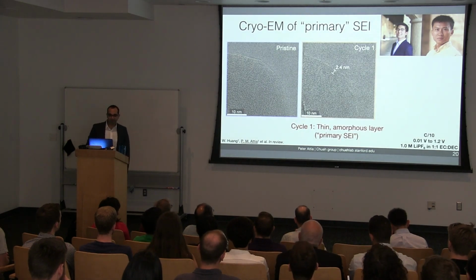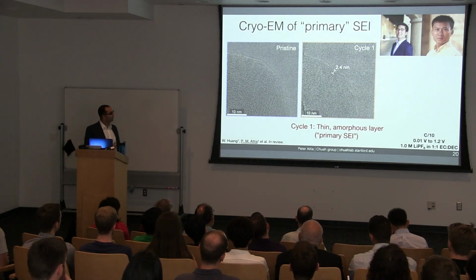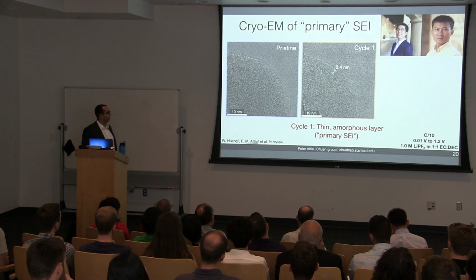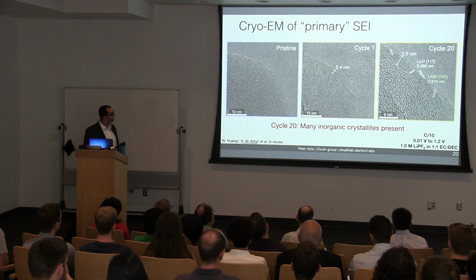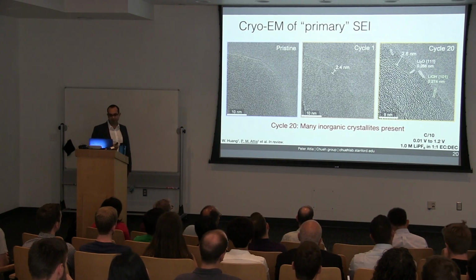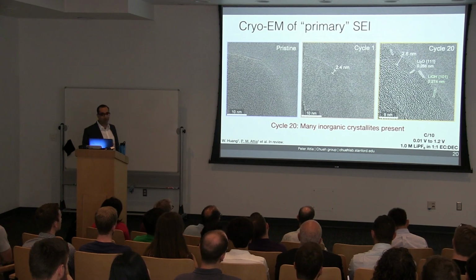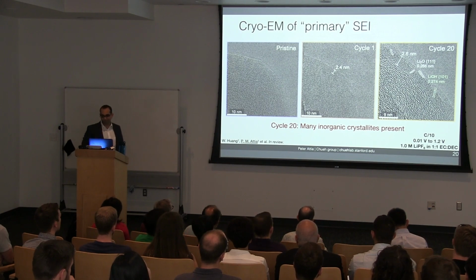After one cycle, we start to see a thin amorphous SEI layer form. We're going to refer to this thin type of SEI, around 2 nanometers thick, as primary SEI. After 20 cycles, the primary SEI involves a highly inorganic structure of small crystallites of lithium oxide, lithium hydroxide, and lithium carbonate. The structure had been theorized before, but with Cryo-EM we're able to directly visualize it.